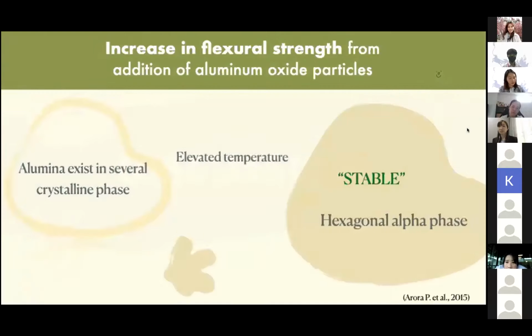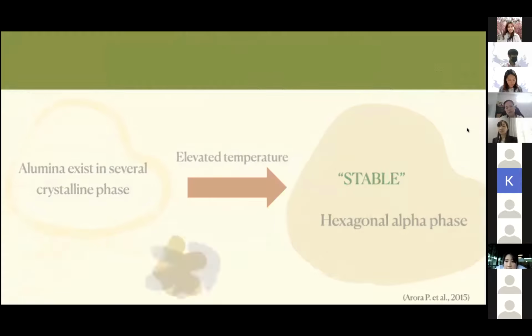Discussion. The increase in flexural strength from addition of aluminum oxide particles can be explained. As alumina exists in several crystalline phases, in elevated temperature, alumina will turn into the more stable hexagonal alpha phase.